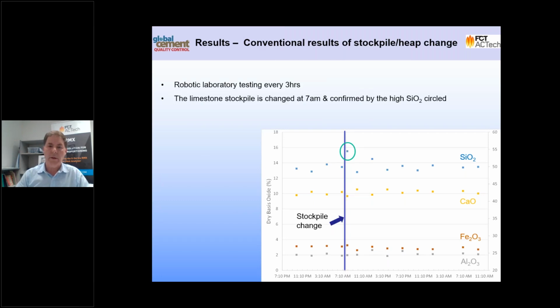So what I've got here is a graph of the laboratory analysis results taken every 3 hours over a 3-day period. And you can see the results here for the silica, the calcium, iron and alumina. And what's indicated here with the green circle is a very high silica reading. And that's indicative of a pre-blend heap change. So what we know is that at this time, there's been a pre-blend heap change. And other than that, that's about as much information that we can see from this graph.